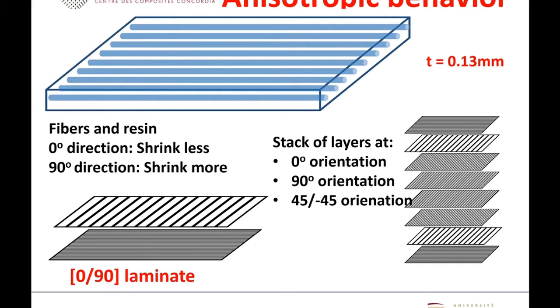So when people make the composite, they use a lot of these fibers. They have the very tiny fibers, and then around each of these fibers, you have some kind of epoxy resin. The epoxy resin can surround the surface, and it is used to bond many of these fibers together. So in this case, you can see the material consists of fiber and resin, and the anisotropic property is that it varies along the fiber direction and transverse to the fiber direction. Along the fiber direction, it's normally very strong and stiff. Transverse to the fiber direction, it may not be.